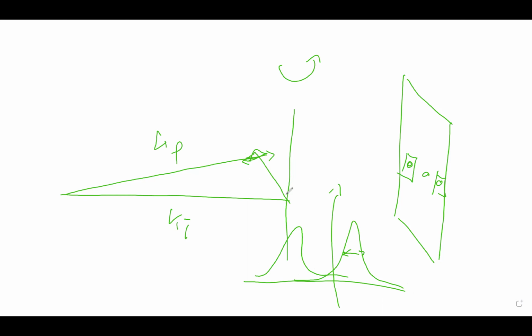So we have the Ewald sphere somewhere here, and then we move our Bragg lattice through the Ewald sphere here, and then we extract the correlation lengths along the field. This is the field direction here, which is parallel. And so if you extract that, you'll get correlation lengths of many hundred nanometers.